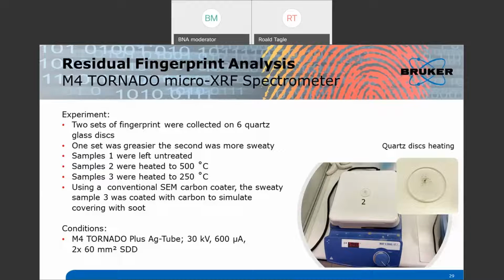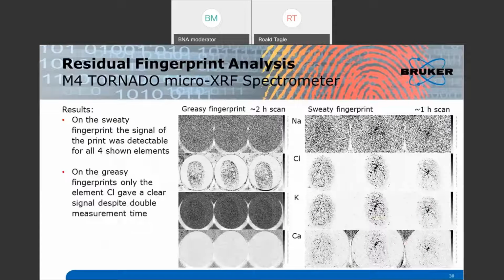Now we would like to see, and the idea is, first, can we detect the fingerprint in the original way? What are the potentials, and how does it look if we try to change or destroy them? So basically from the experiment, we see here the greasy fingerprint on the left side. On the right side, we see the sweaty set of fingerprints. And this was the first quick scan to get an idea, on an untreated, original sample, so that we have three sets that are more or less identical to start with.